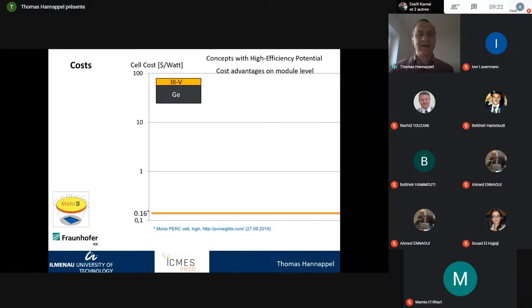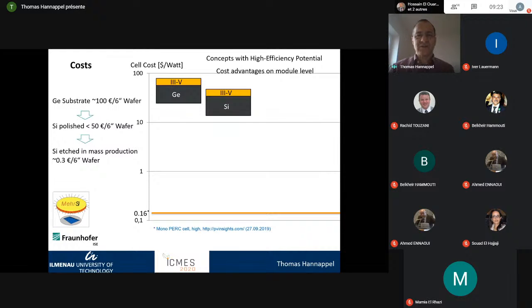What you can see here is the cell costs in dollars per watt. Normally, these very costly high-performance multi-junction cells are grown on germanium. In this industry area, germanium is the workhorse so far, and you can grow almost perfectly III-V semiconductors on top of it. However, it's of course too expensive to get the costs down. This is a first step, and that's what we are also tackling together with our partners, which I already mentioned, is to combine the III-V layers with silicon. However, this is also still expensive if we regard the current production routes of growing III-V on silicon.